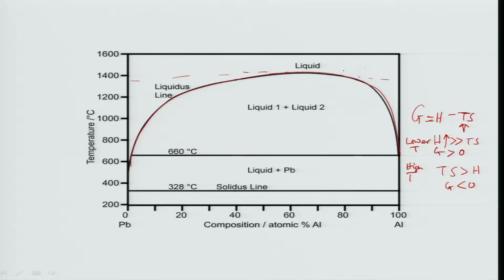If you take a kerosene and water mixture and keep on heating, after some time it will mix. At about 40 degrees Celsius it starts mixing, but do not heat beyond 65 degrees Celsius, because kerosene will burn and it can create an accident. So, if you keep on heating, after some time the entropy effect, because T is there as a multiplication factor, will be stronger than the enthalpy, which is positive because of the disliking of the atoms, and it will mix. That is why there is a critical temperature, called TCR, beyond which there is a simple miscible liquid.